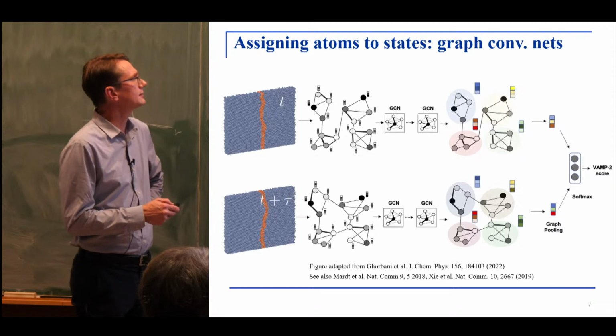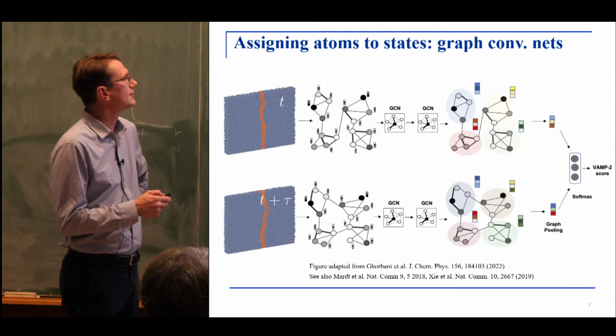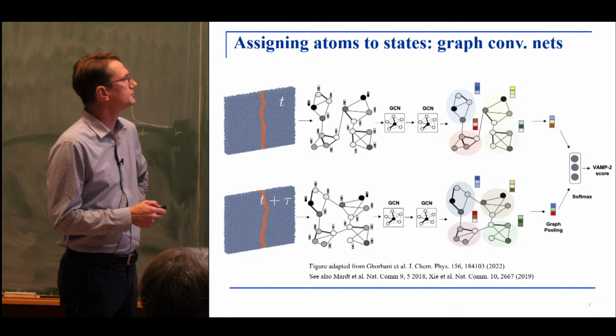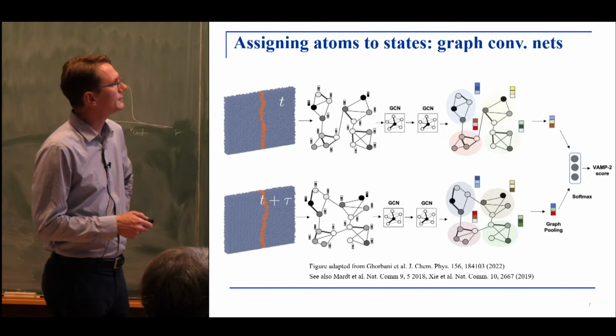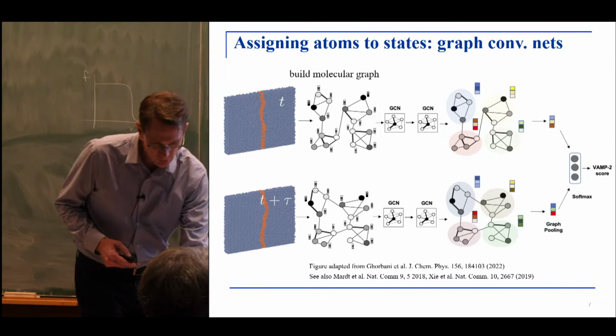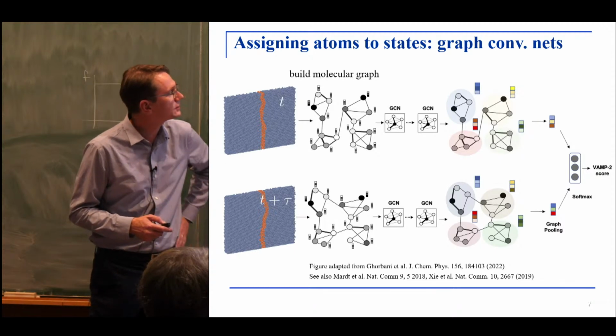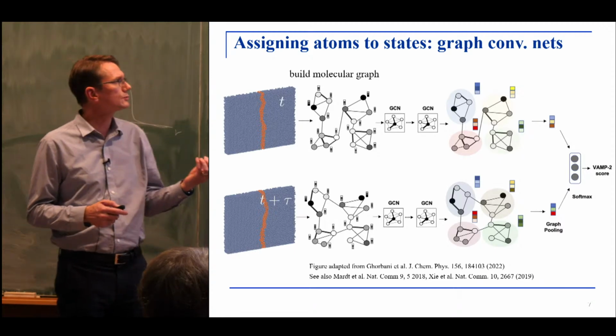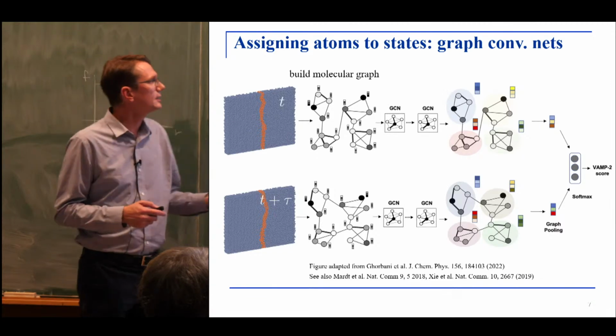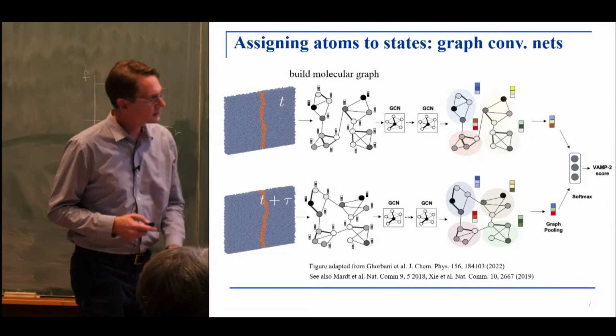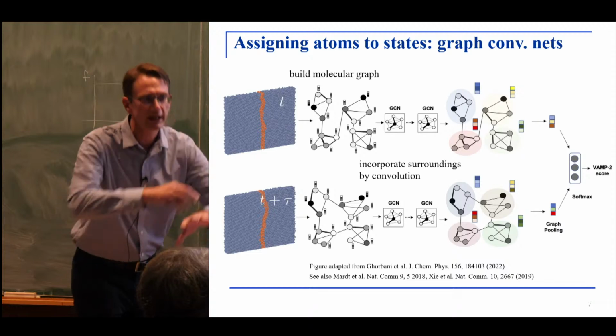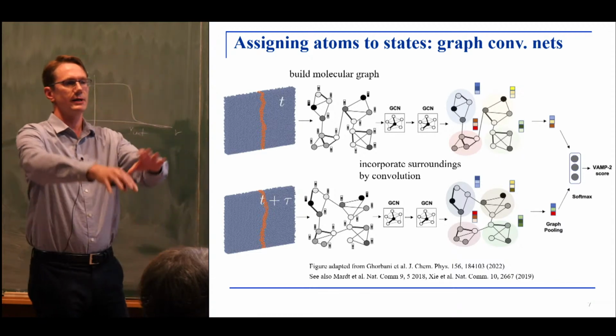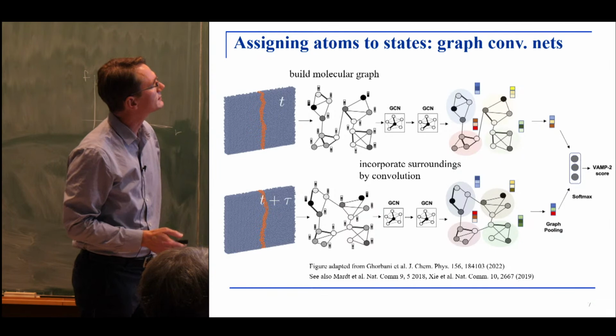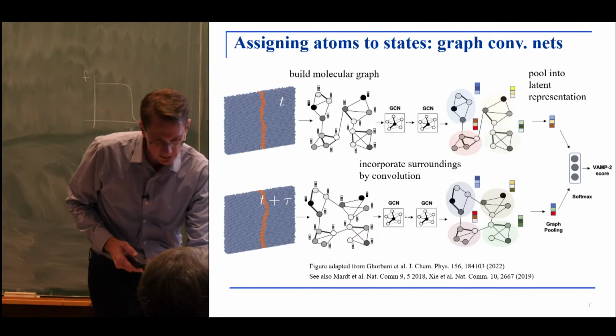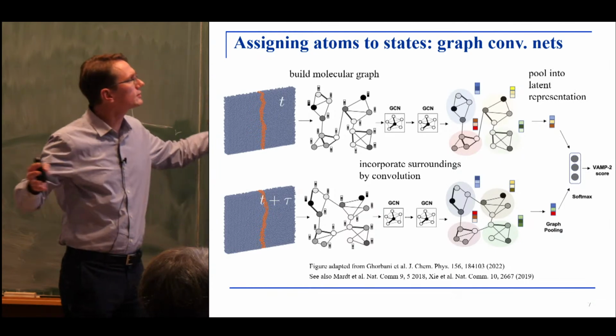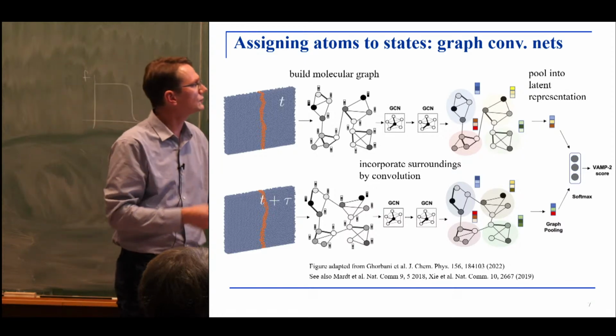Here in this case, it's the example of a grain boundary where we have an interface here that you can see in red at two different times. The first step that we do is to use these graph networks to come up with a local description of the particles that was described quite extensively by Laura this morning. One uses convolutions to spread out the information over a larger range in space. Then one does some sort of pooling operation to collect all this information into a large feature vector.